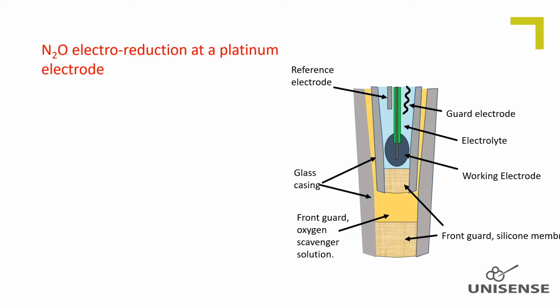The nitrous oxide microsensor is built into a second tapered glass casing, also equipped with a silicon membrane, and this is the front guard. It contains an oxygen scavenging solution consisting of an alkaline sodium ascorbate solution, which is a strong antioxidant. This solution reduces oxygen, which would otherwise interfere with the nitrous oxide measurements because oxygen is readily reduced on the platinum working electrode. The membrane is permeable to nitrous oxide.